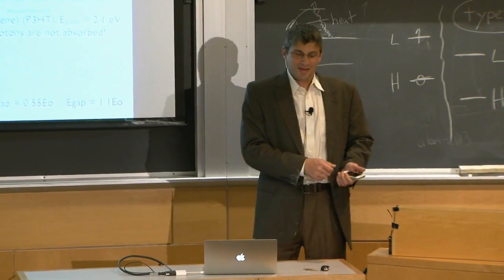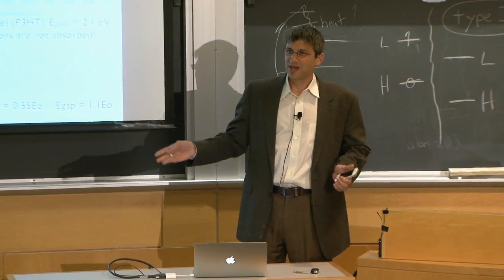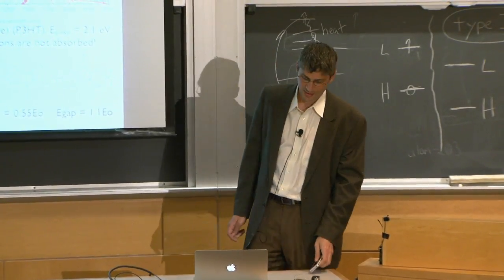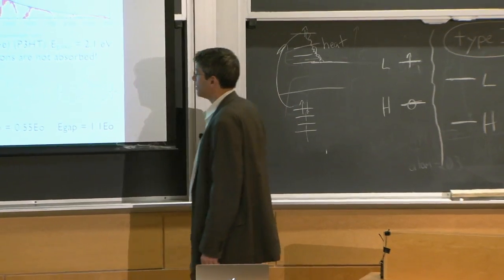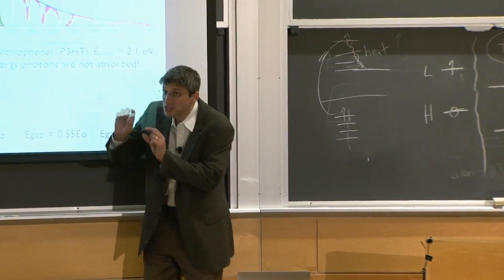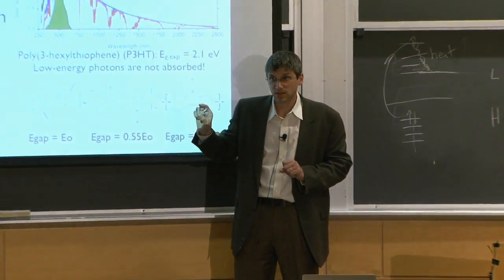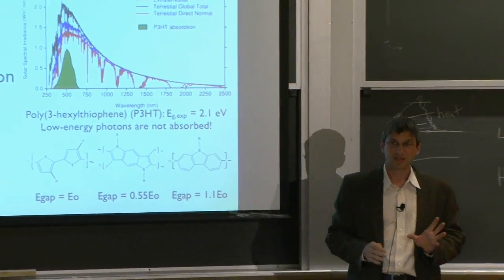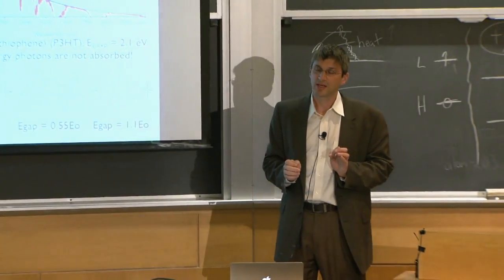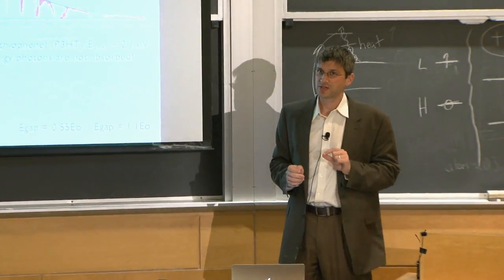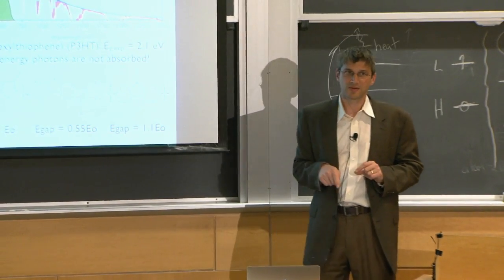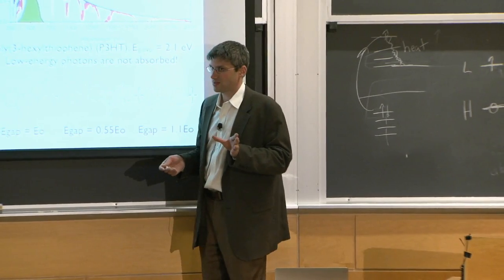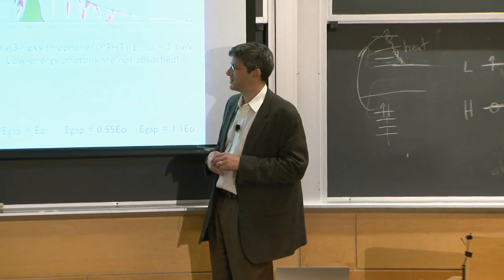And you wait the whole day, and you get like 2 minutes of talk time. They're very low efficiency, okay? But they're getting better. And actually, the research efficiencies of polymer cells are now almost 10%, 9, 10%. That's pretty exciting. Remember, research efficiencies, what you buy is very different. It's still very low, right? 2%, maybe 3. That's not what they say, but it's what people measure.